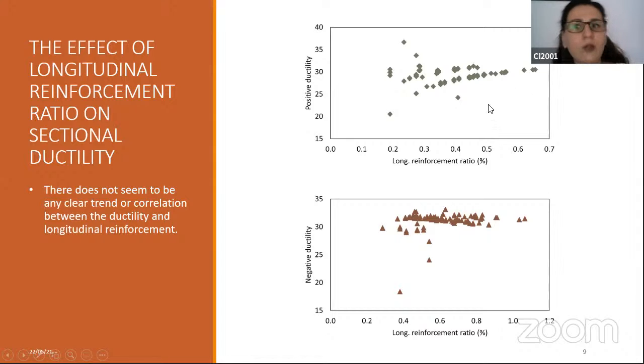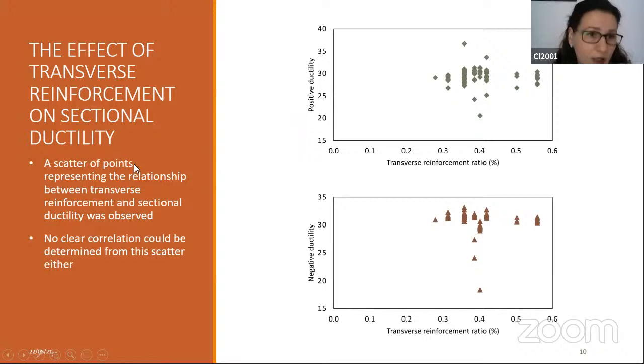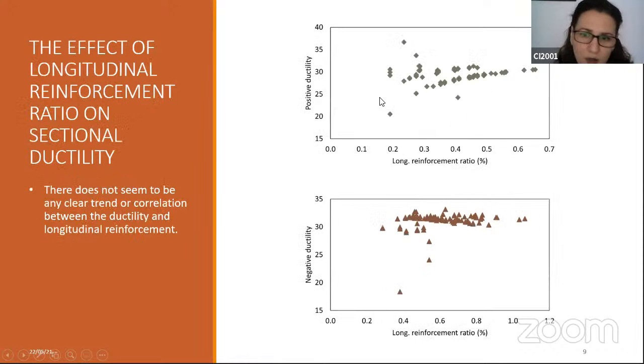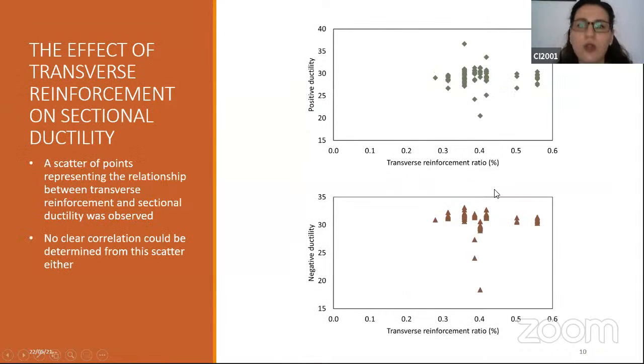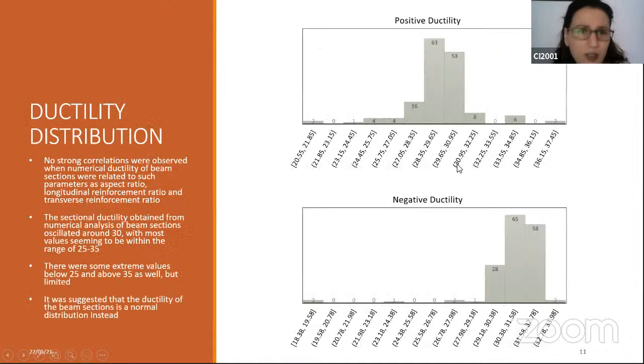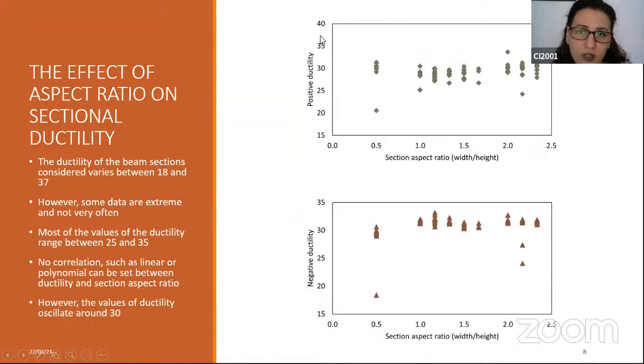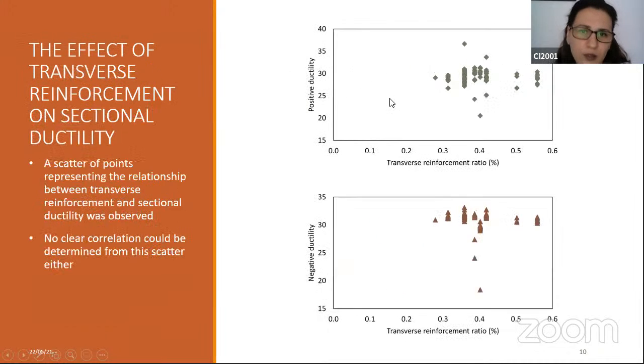when higher reinforcement ratios were present, but there was no clear correlation that we could obtain. Similarly, again, for the transverse reinforcement ratios, there was quite a scatter and no clear trend at all. For example, in the reinforcement ratios, there was some sort of trend, a bit of convergence, but in the transverse reinforcement ratio, this was not observed. So we thought, okay, none of these parameters alone seems to have a clear correlation with the ductility. And we also observed that the ductility values seem to range in a certain value interval.